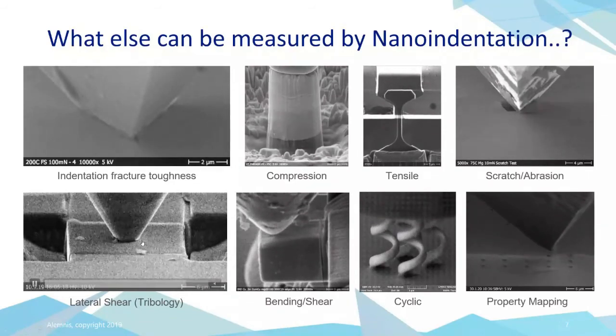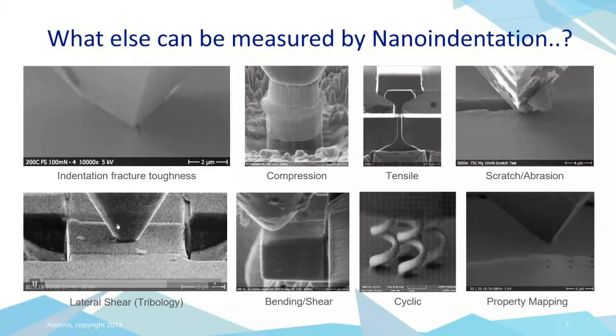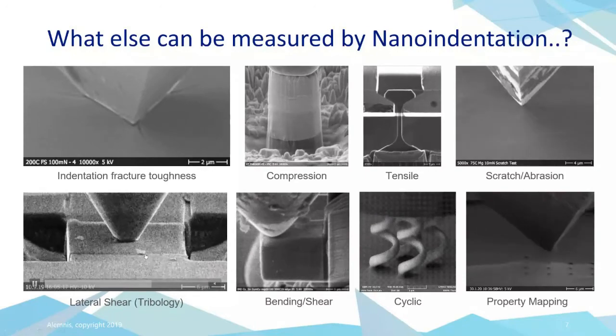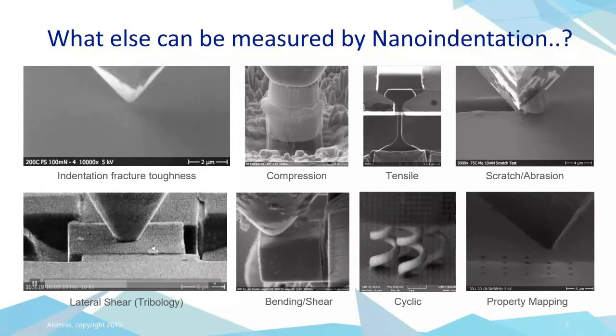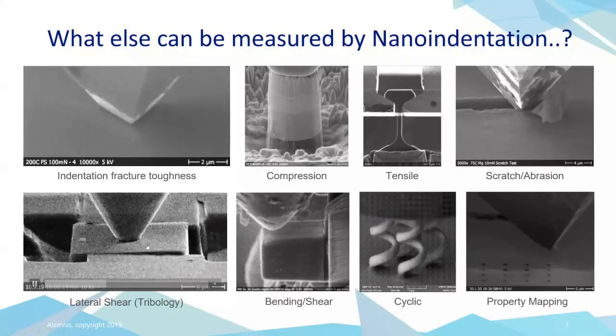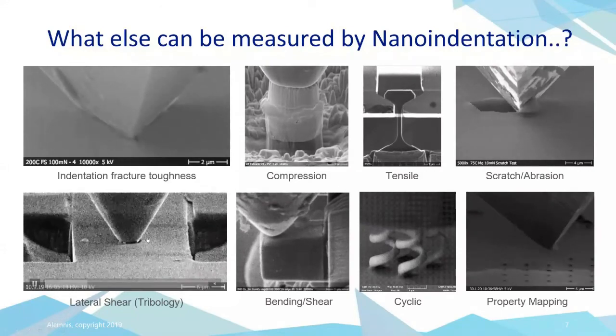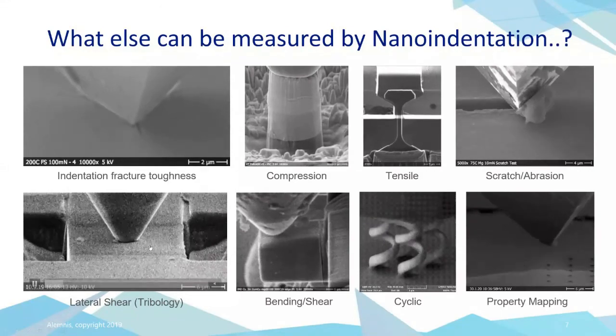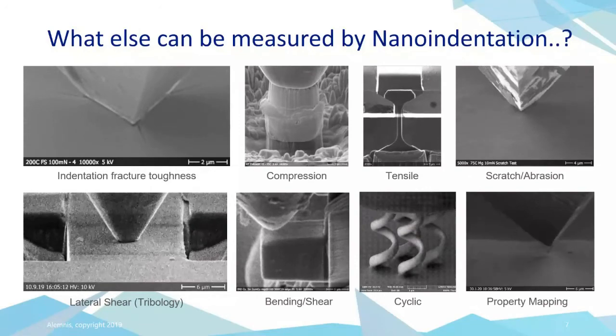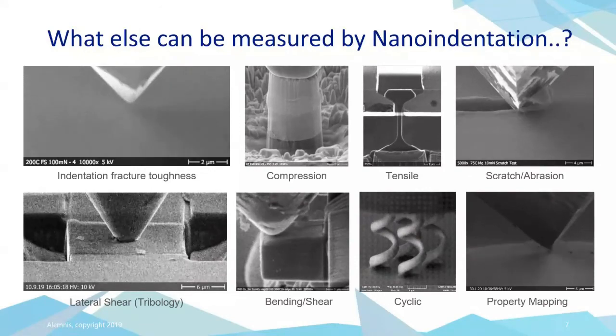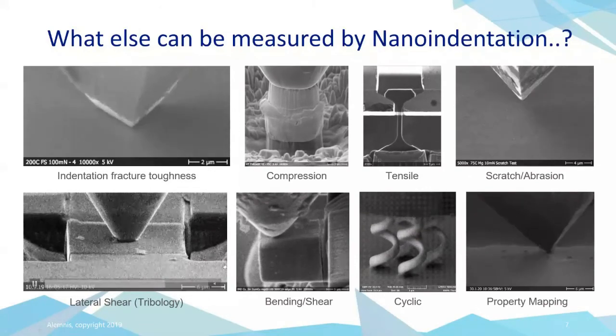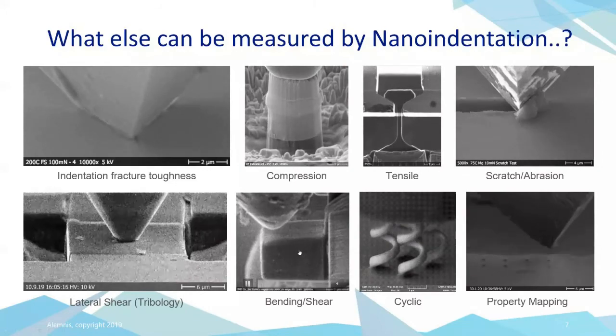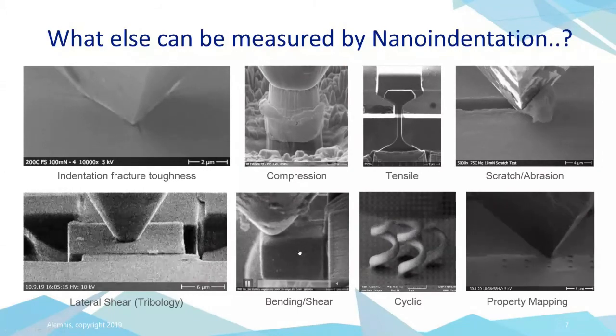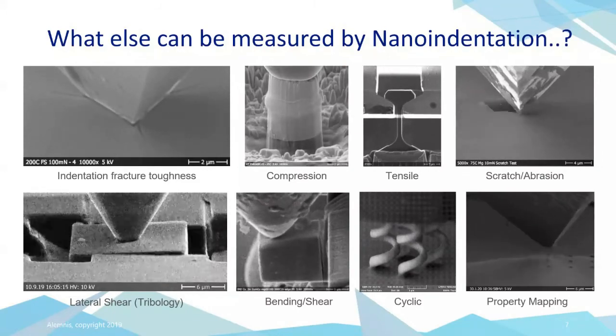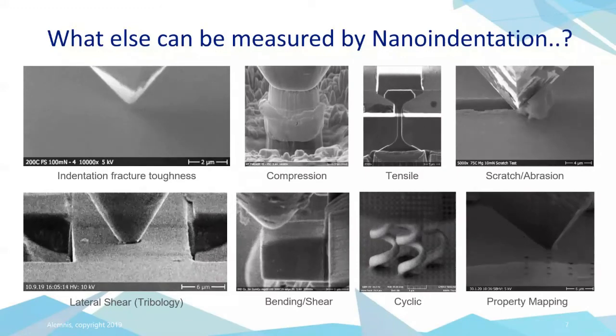Down here on the bottom left, we've got lateral shear. So this is a more specialized application where we're picking up a fiber in a composite matrix, and we're basically displacing it tangentially so we can break the fiber out of its matrix and therefore measure the interfacial shear strength. So this would be a typical tribology type test. Then we've got bending and shear, so beam bending experiments using beams that are cut by focused ion beam.